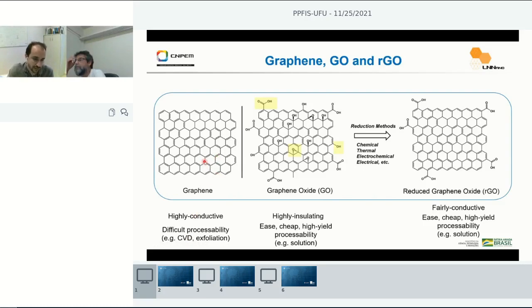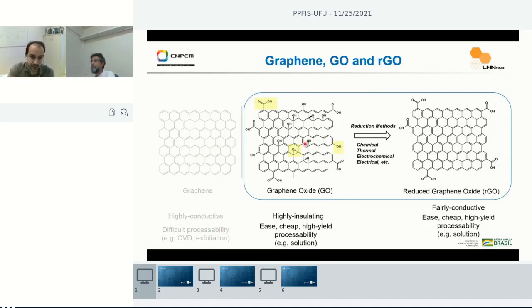You can use, for example, chemical vapor deposition or exfoliation, like the Scotch tape method that Geim and Novoselov used. And these methods are quite expensive in the case of CVD, or not scalable in the case of mechanical exfoliation. But graphene oxide seems to be very interesting. It's also a monolayer of carbon atoms, but it presents many different types of oxygen groups, both in the edges of the flake, but also in the basal plane. And because of this, it's a very insulating material.